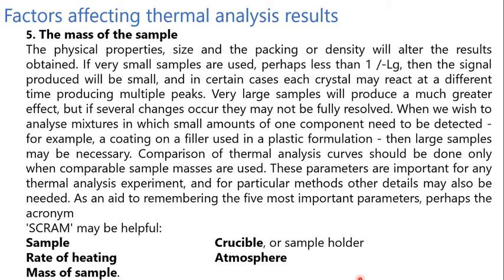When we wish to analyze a mixture in which small amounts of one component need to be detected, for example a coating or a filler used in a plastic formulation, then large samples may be necessary. Comparison of thermal analysis curves should be done only when comparable sample masses are used.